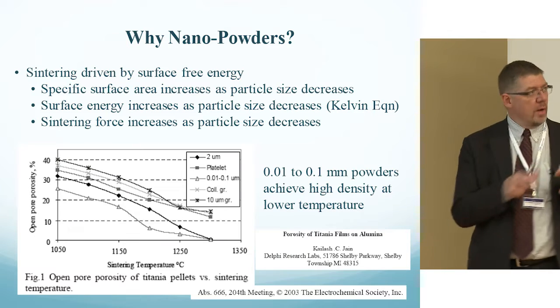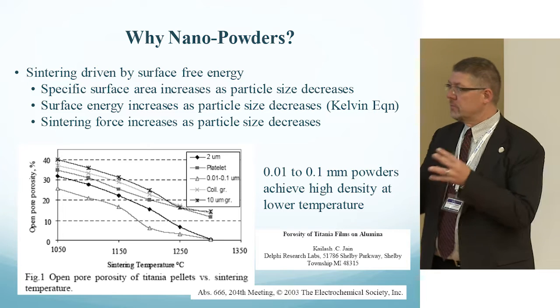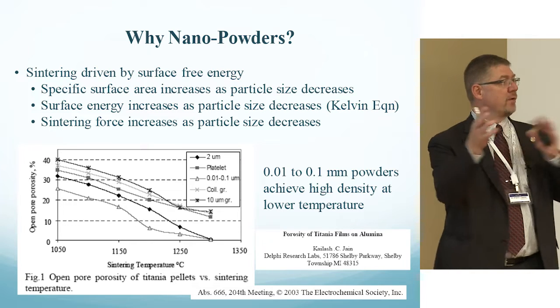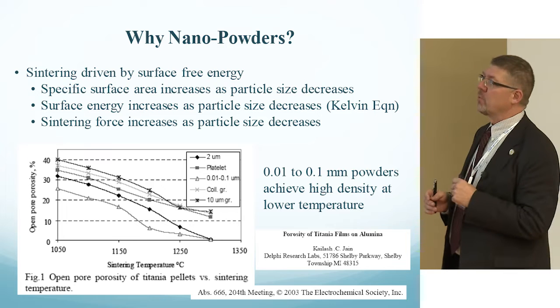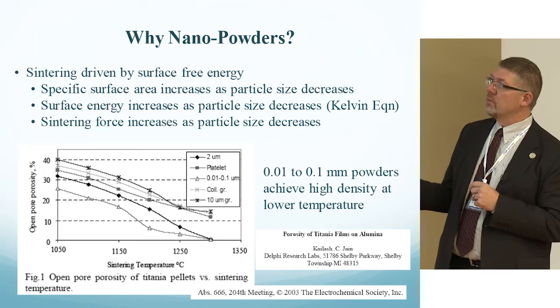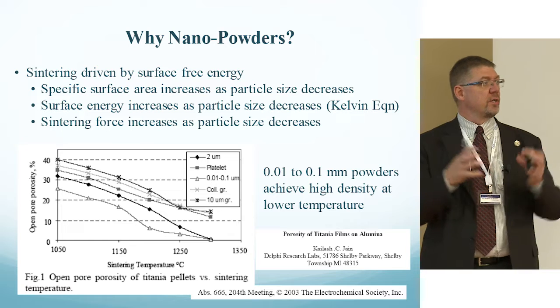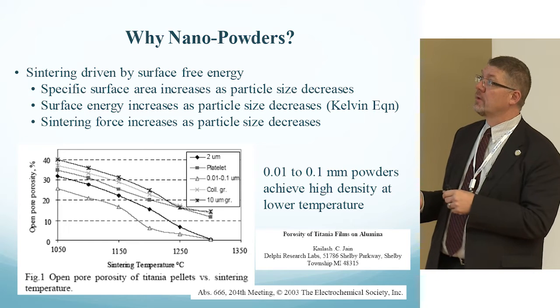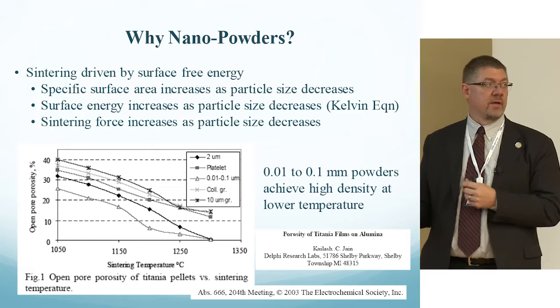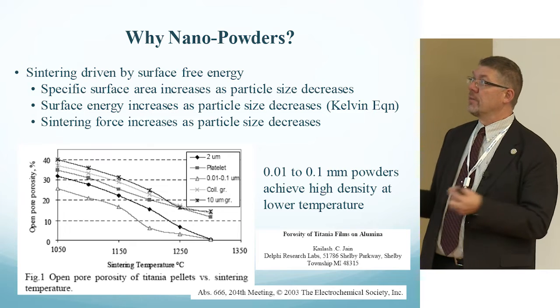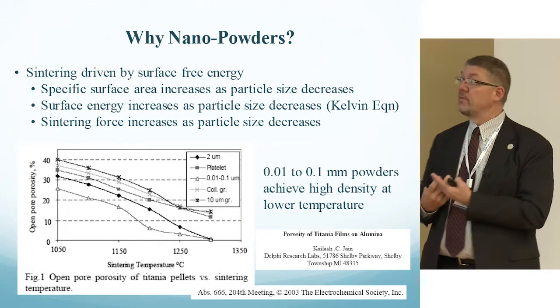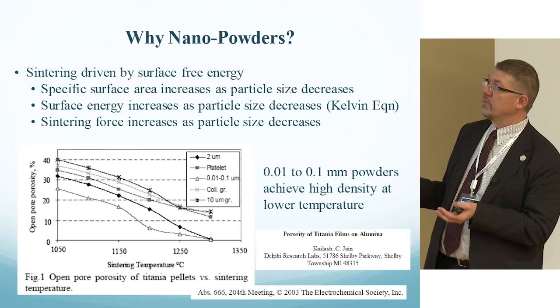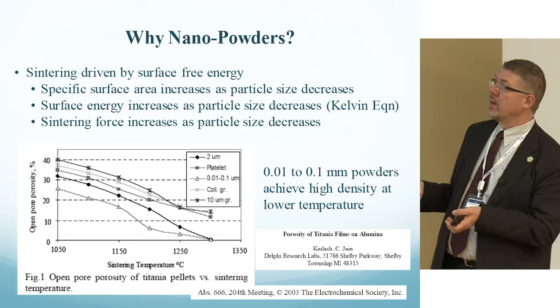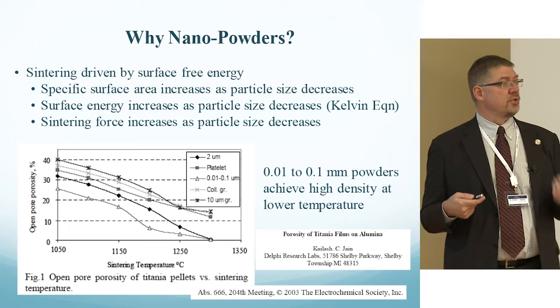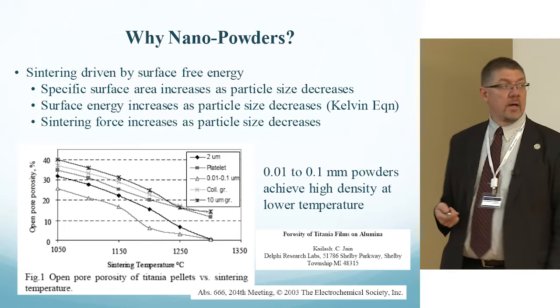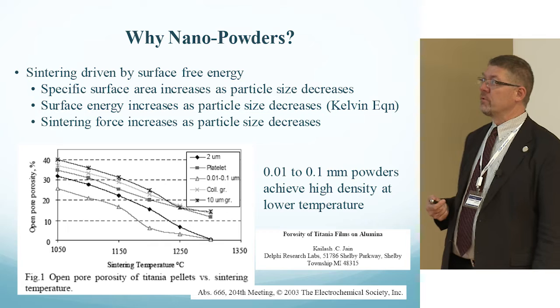And so why nanopowders? Why do you want to keep these powders small? The thing that's impressed me about the meeting so far is how many people have been working on nanopowders and various types of processing here. So you know that the sintering is driven by surface-free energy of these particles coming in close contact to each other. It increases as the particle size decreases from the Kelvin equations, and the sintering forces increase as the particle size decreases. So somewhere between 0.1 and 0.01 millimeters, you can actually achieve very high density materials at reasonably low temperatures.